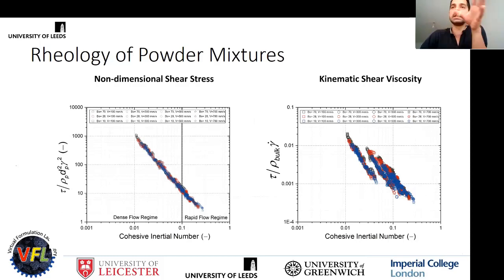We've also done a lot of stress analysis in DEM on the same type of mixture. To give you a brief, we have investigated more than 100 mixtures in our study. And what we found, we developed master curves, or generic curves, where we represent the data in terms of non-dimensional shear stress, which you see on the left-hand side, which is shear stress divided by the inertial stress, as a function of the inertial number, which is the ratio of the microscopic deformation timescale and the inertial timescale. And we've got a unification for all sorts of mixtures as well as different strain rate conditions. From that, we can derive the kinematic shear viscosity curve. And now we have a generic curve on which we can develop our toolkit.